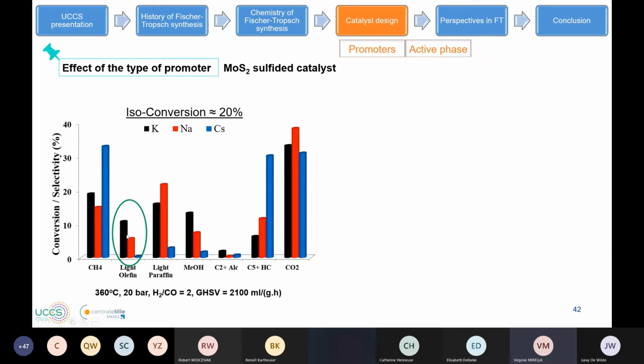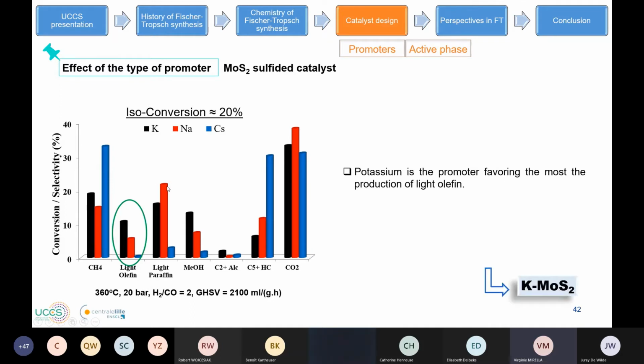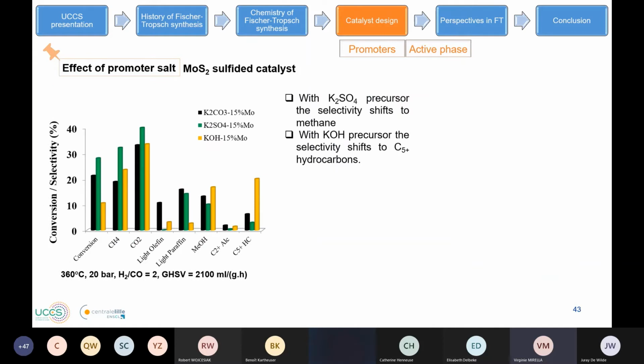So for our sulfide catalyst based on alumina support, we observed that we have different rates of selectivity in production of olefin, depending on the promoter that we use. We observe that we have better selectivity in olefin when we use potassium. So potassium is the promoter that favors the most the production of light olefin. So it was more interesting to continue our study with potassium and molybdenum sulfide catalyst.